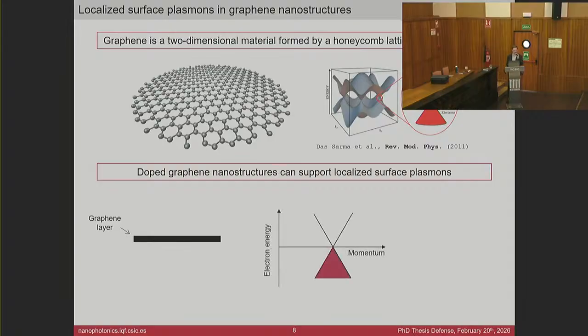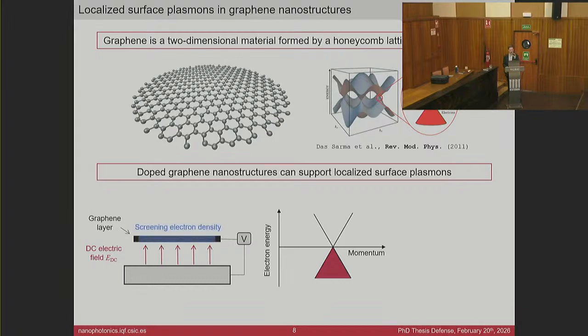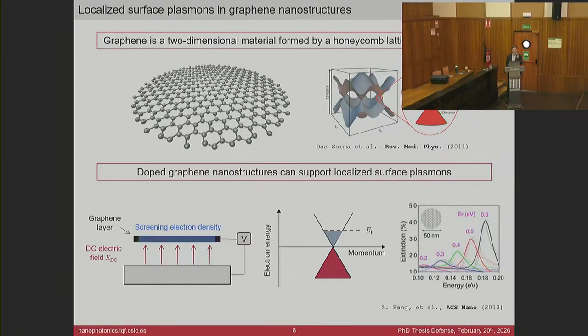A well-known method is the so-called electrostatic gating, in which we apply a potential to graphene in a sort of capacitor configuration, and in this way, our graphene layer will get charged, and the conduction band will get filled up to a certain Fermi energy. And by playing with this Fermi energy, we can obtain plasmons that are tunable, that have different properties. We see here a blue shift as we increase the Fermi energy.